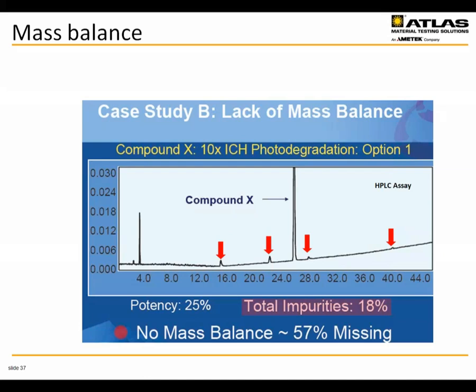One of the key aspects of the ICH requirements is not only understanding and testing the photodegradability of the product, but also understanding what the degradants are and being able to account for the majority of them. There are two key aspects of photostability testing: a certain minimum testing requirement called confirmatory testing, and a forced degradation test — where you deliberately photodegrade the API far in excess of normal conditions to validate your stability-indicating assays and show that you can account for the mass balance.